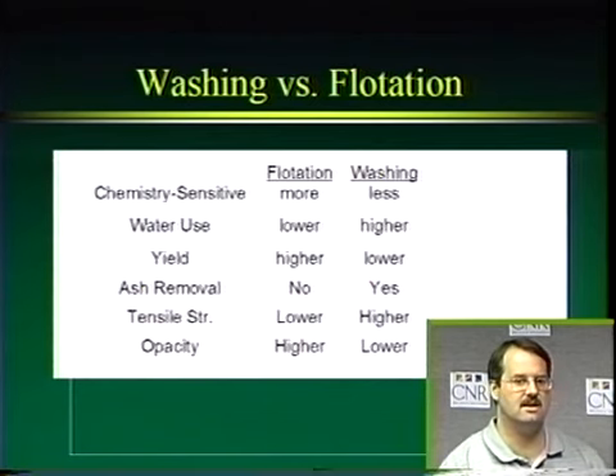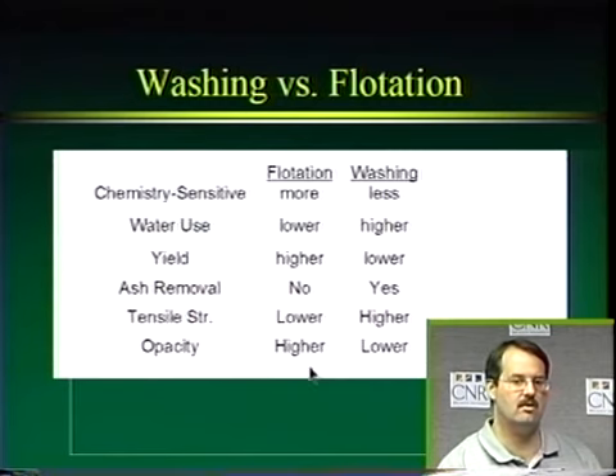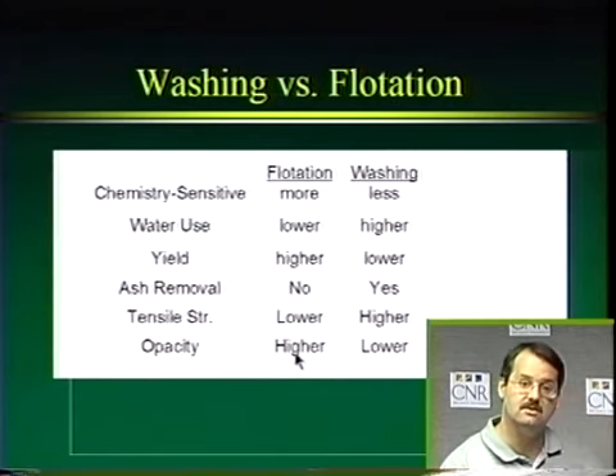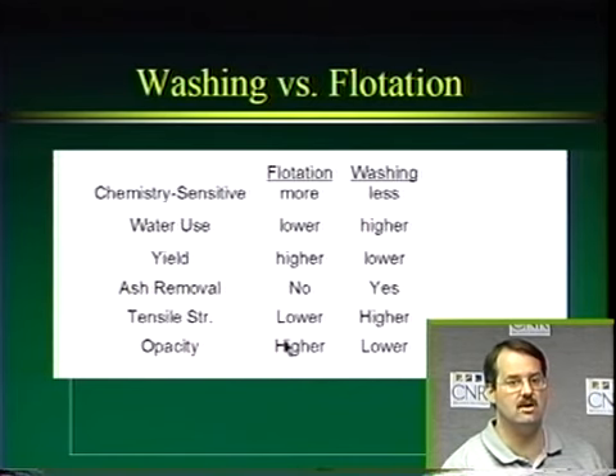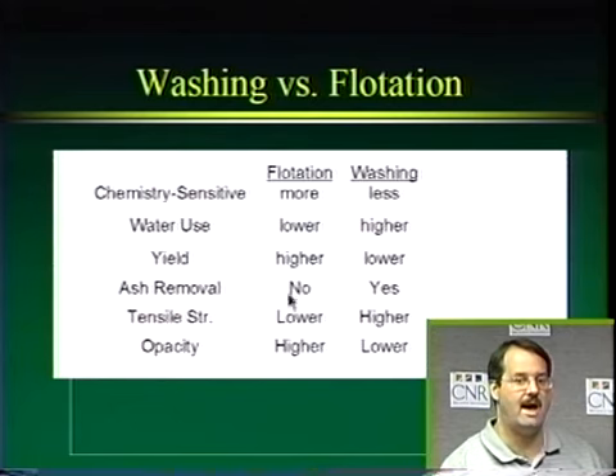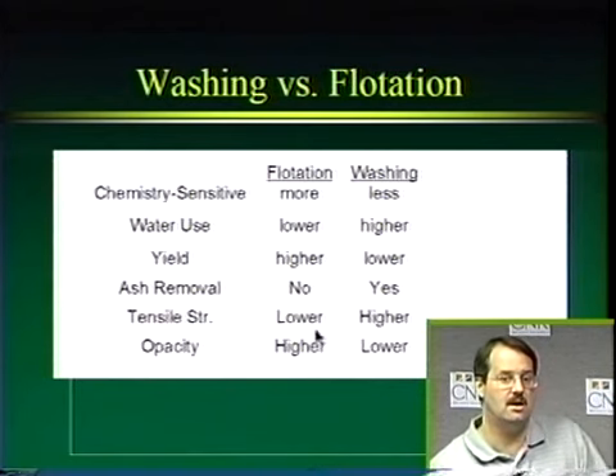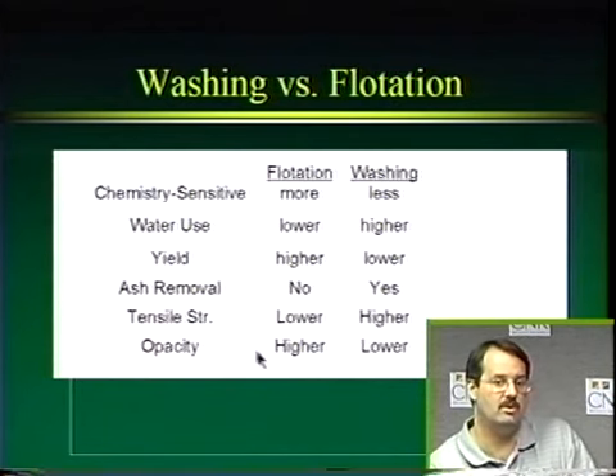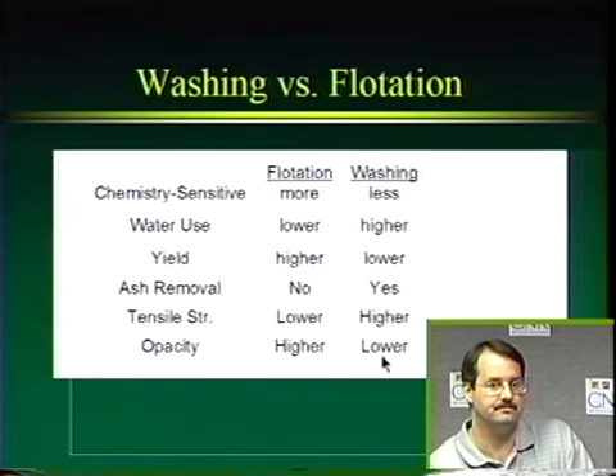And then the last thing is our opacity. Well, our opacity of our resulting pulp is going to be higher with flotation and lower with washing. Why do you think that? Well, it goes back to the ash removal. Ash actually gives us a lot of opacity because there's a lot of specific surface area to scatter light with the ash. So for flotation, we're going to have pulp with a higher ash content and higher opacity. For washing, where we've gotten rid of our ash, we're going to have a lower opacity.